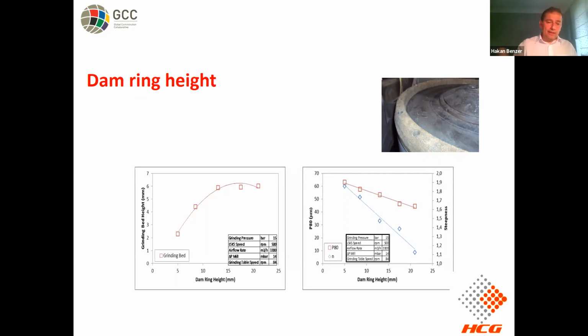So the dam ring height is quite important, where you adjust your grinding condition in a vertical roller mill. As you increase your dam ring height at a certain point, the grinding bed height is increasing, and then it's stabilized. And if you increase the dam ring height, your product size gets finer, and the steepness of your material is dropping.